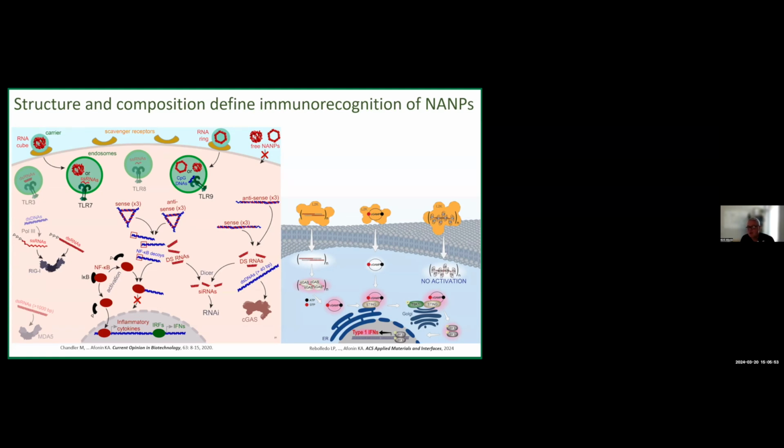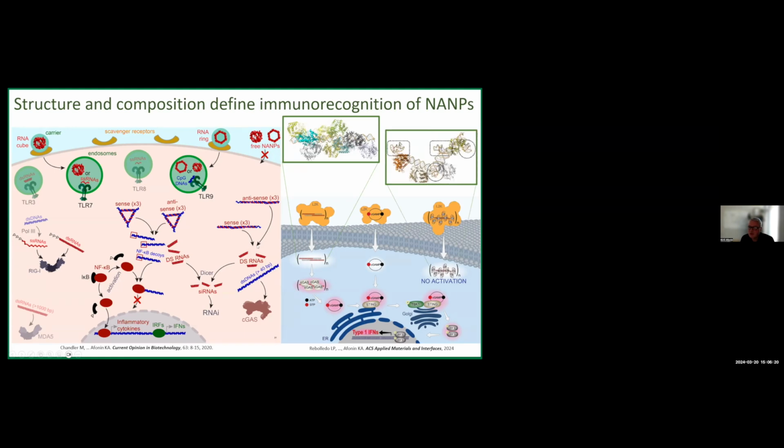with the therapeutic moieties. For example, if we take fiber-like structures and introduce them into human cells, they can be recognized via the cGAS-STING pathway because cGAS can easily recognize those fibers and bind to them, as can be seen here on the predicted models. However, if we put some therapeutic moieties on those particles, depending on the density and orientation of those therapeutic moieties, they can shield the NANPs from being recognized by cGAS, and therefore those NANPs become undetected.